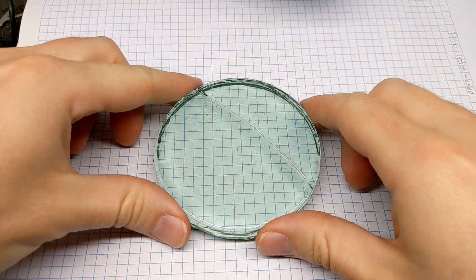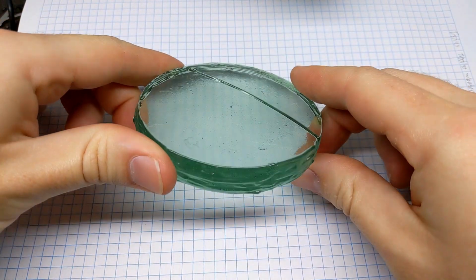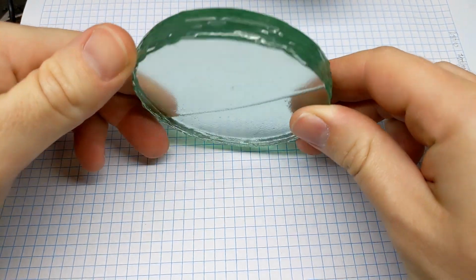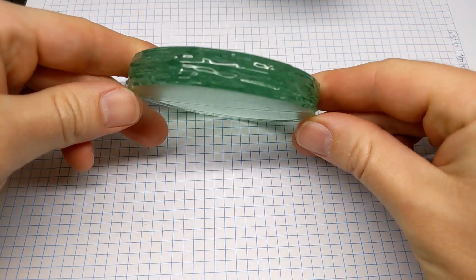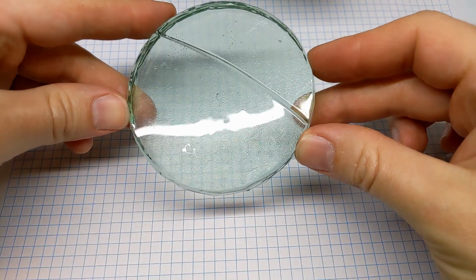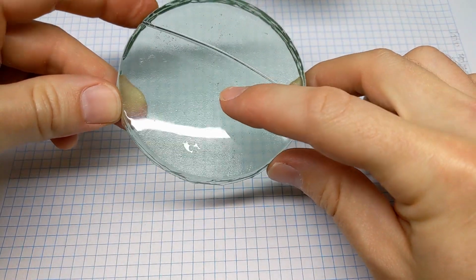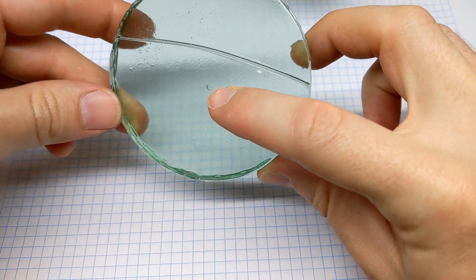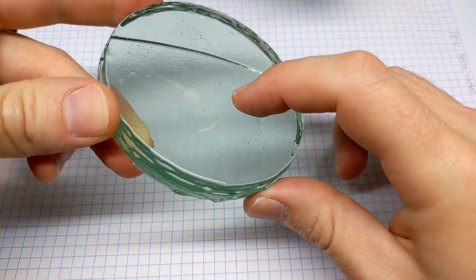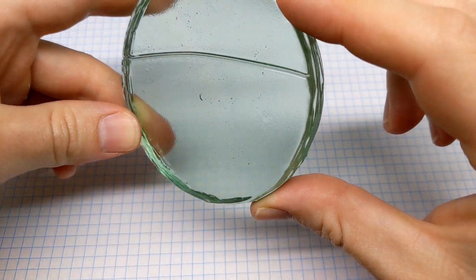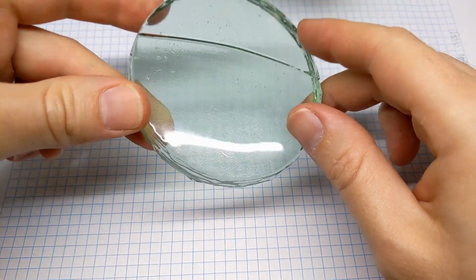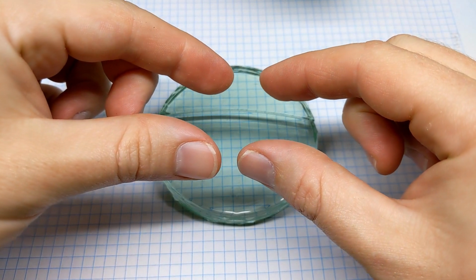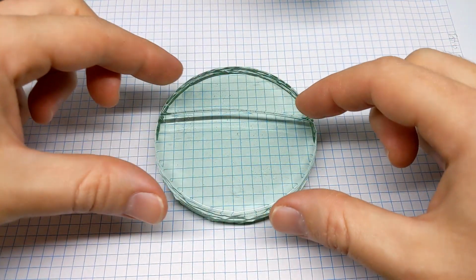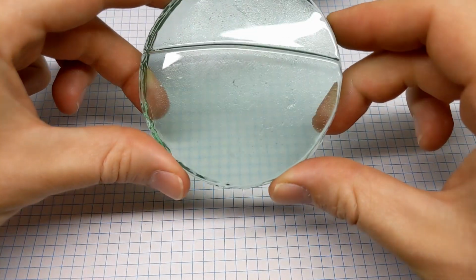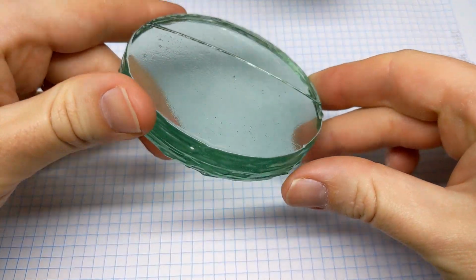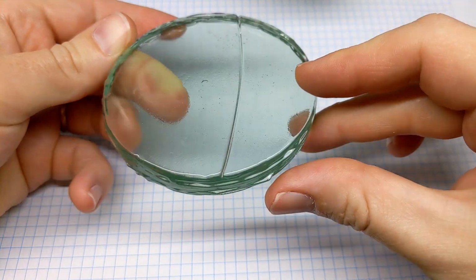So here is the glass that's been fired twice and soaked in potassium nitrate at 400 degrees for an hour. Afterwards, I gave it a gentle donk with a hammer, just because I like the sound of it, and it sort of cracked it a little bit. So it's a weird crack. It's sort of like a truncated cone with a small circle at the top, and then the crack seems to extend downwards in a circular, expanding crater kind of fashion. It's kind of hard to see unless you get the light just right, but that was surprising.